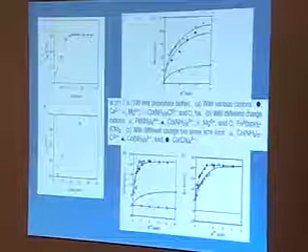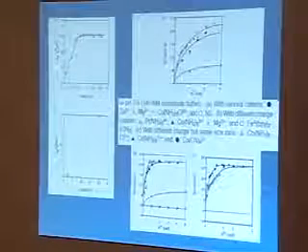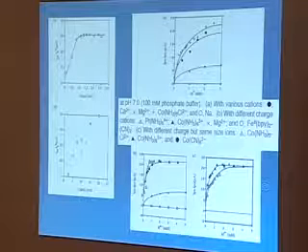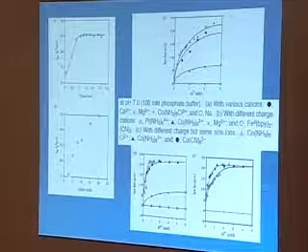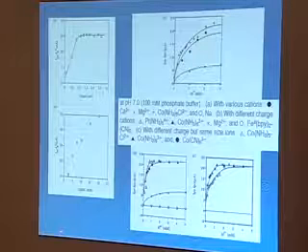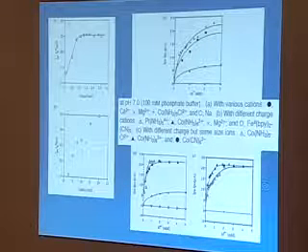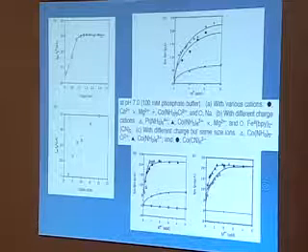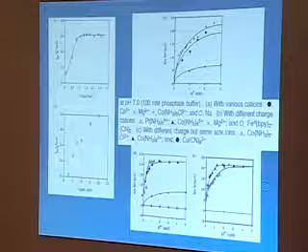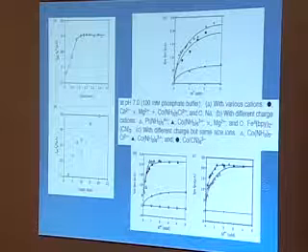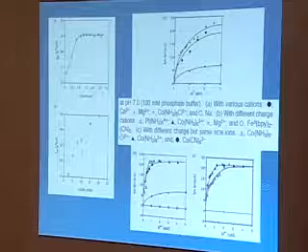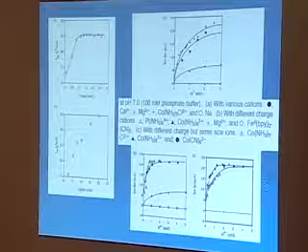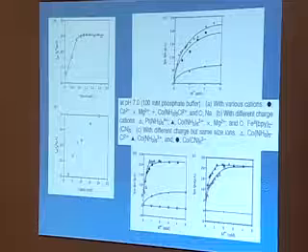Now looking at that difference in peak current in the cyclic voltammogram with coverage, you find out at low coverages of the ruthenium there's a linear response, and then it saturates. Putting more on doesn't change anything. Likewise, you see a fairly linear response with the amount of glucose oxidase you have out in solution. And it turns out that if you keep your glucose oxidase concentration below about 20 micromolar, then you follow nice Michaelis-Menten kinetics, for those of you who like biochemistry. So we did that, just so we didn't have the kinetics of the enzyme mess things up.